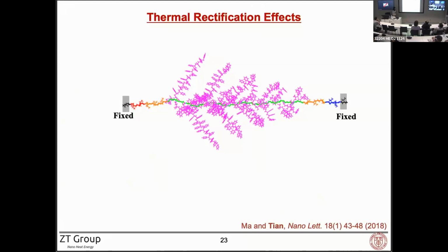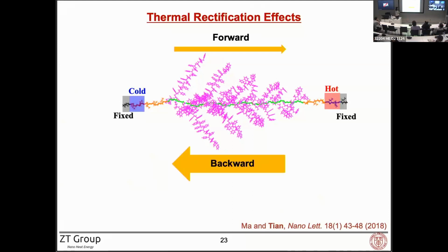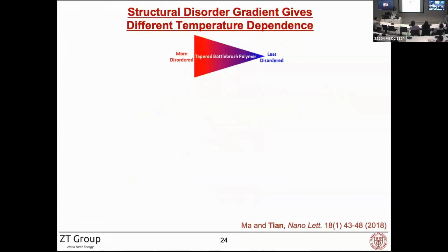And we fix both ends and introduce a heat reservoir to record the heat current in the forward direction. Then we flip the directions, flip the heat reservoirs, to record the heat current in the backward direction. Very surprisingly, we got the backward heat current to be larger. This is opposite to what people observed in asymmetric carbon nano-based materials, where they typically observe a higher heat current from wide end to narrow end. So we spent quite some time figuring out what's going on, why we're getting this backward heat current being larger.